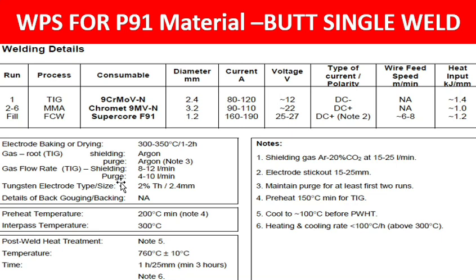Preheat temperature is 200 degrees centigrade minimum, interpass is 300 degrees centigrade. And for post-weld heat treatment, it is mentioned to cool to 100 degrees centigrade before PWHT. Same temperature we have to follow, 760 plus or minus 10, that is the maximum temperature. Time is 1 hour per 25 mm, minimum 3 hours. Note 6 mentions the heating and cooling rate is less than 100 degrees centigrade per hour.